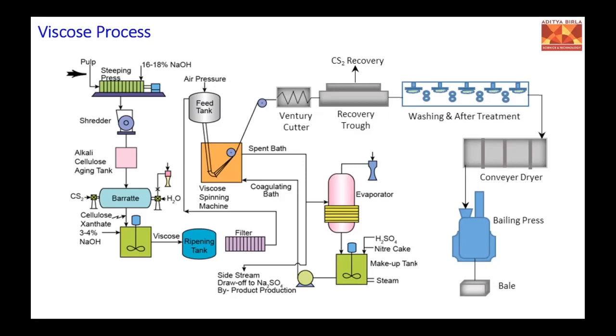The alkali cellulose is then allowed to mature for the depolymerization process, so it gets depolymerized to achieve a desired DP. The major step of the viscose process is xanthation, where it is allowed to react with CS2 and forms cellulose xanthate. We form cellulose xanthate because we want the cellulose to be in a dissolved state, a polymer solution, so that we can spin it from the spinnerets. We dissolve it in dilute alkali and form a viscous solution which looks like honey. Obviously we can't compare it with honey, because honey is thicker and more viscous.